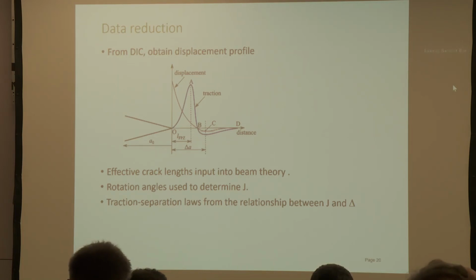So with the DIC, we can track out the values of effective crack length, which we can feed into the beam theory. We can track out rotational angles, either using the DIC method or using inclinometers. That's been done by several other groups. And then we can measure traction separation laws. And we can do that simultaneously whilst measuring J for the adhesive.